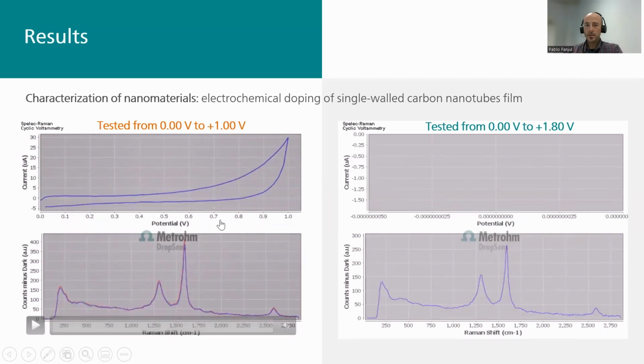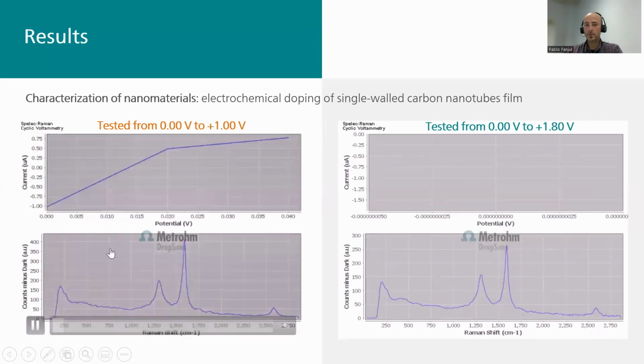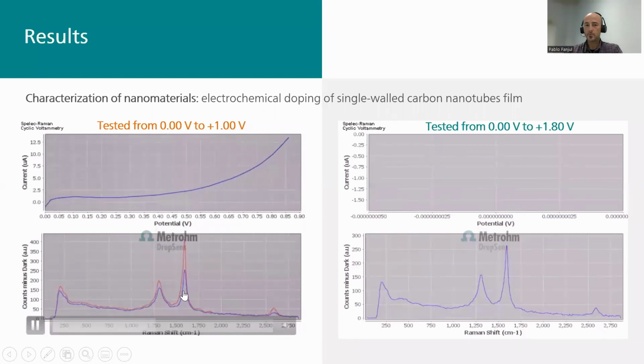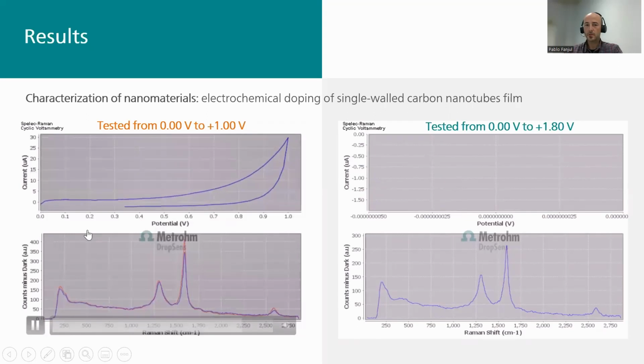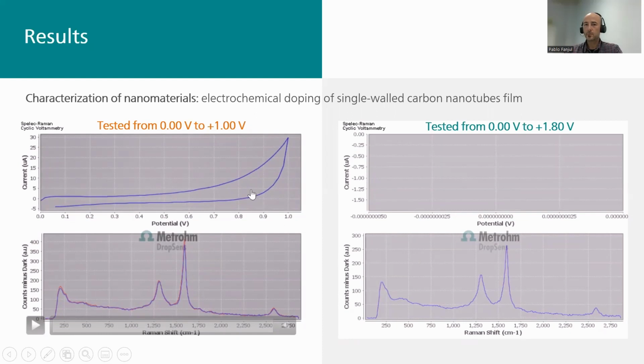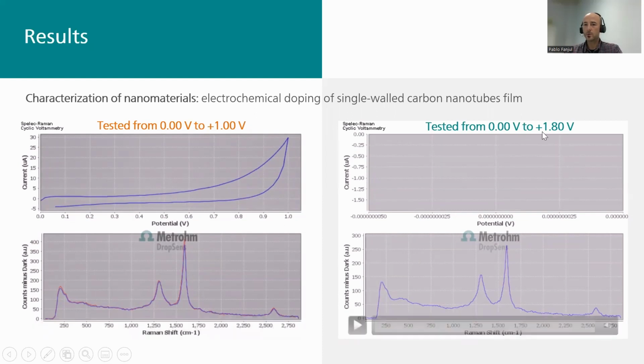You will see that during this cyclic voltammetry, the ratio between the intensities of the D and the G band is going up because the defects are increasing a little bit, and the sp2 structure is going down. So you can see this band is going down a lot. So the ratio is changing, but in the backward scan, we are coming back almost to the initial state. So we are generating some defects during the oxidation process, but we are recovering the initial structure in the backward scan. However, what happens if we change the electrochemical window and we oxidize up to 1.8 volts?